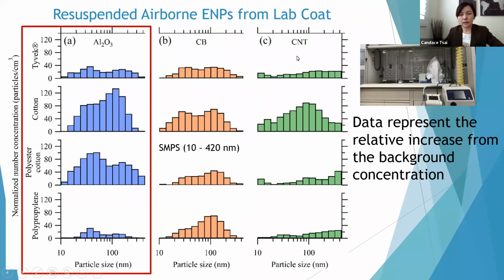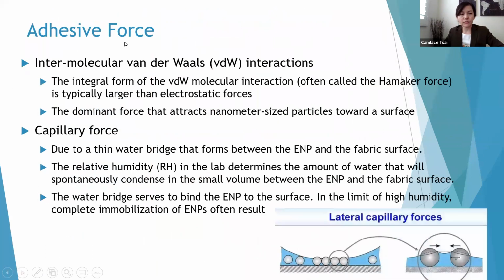Again, like I mentioned, because of different levels of contamination, the aluminum oxide gets the highest. But it's very consistent that we observe cotton and polyester cotton show a very similar result throughout 3 different nanoparticles. They all release the highest.